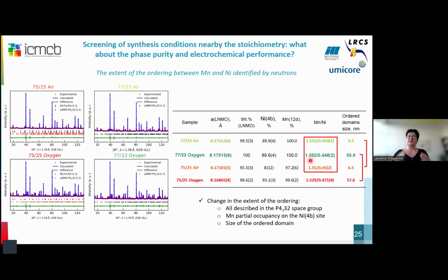So in fact, this combination of X-ray synchrotron diffraction and neutron diffraction allows us to really describe these materials. All of them have to be described in the ordered space group P4332, and not in the disordered space group Fd-3m, with more or less extended size of the ordered domains. And we have also shown that we have a manganese partial occupancy on the nickel 4b site. You can see it can vary from 2% to 5% for that kind of materials. And then we also have different sizes of ordered domains.